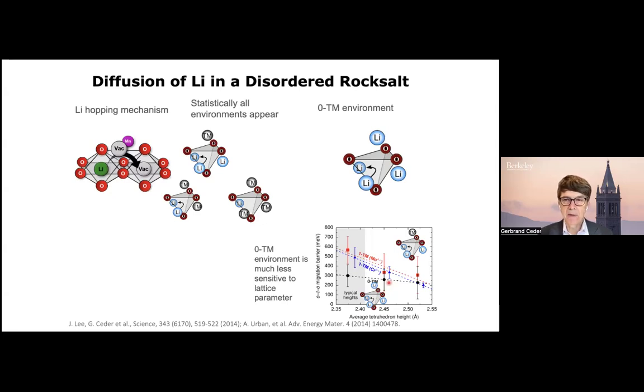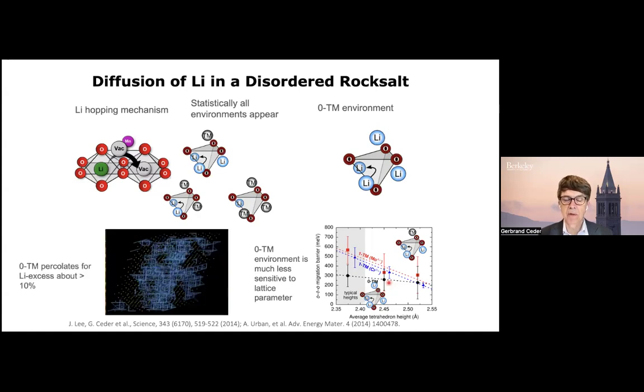And so the idea was that these channels are active for diffusion even in disordered materials. But of course, you need enough of them and they need to percolate. What we found was that you needed 10% lithium excess. If you had 10% lithium excess, and the ions were all randomly distributed, and I'll come back to this, you could make them percolate and get lithium transport through a fully cation disordered material.